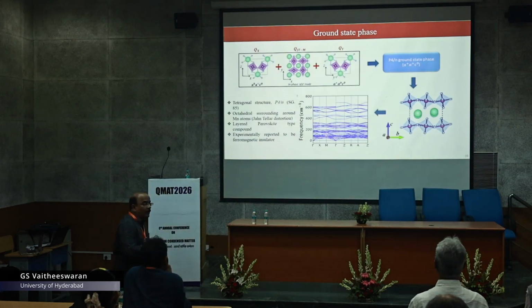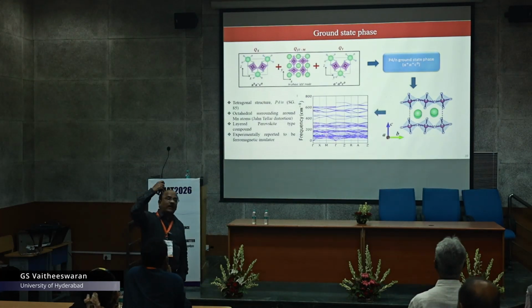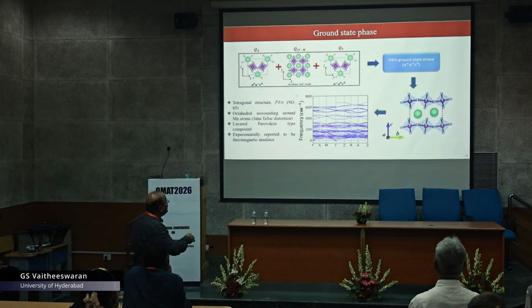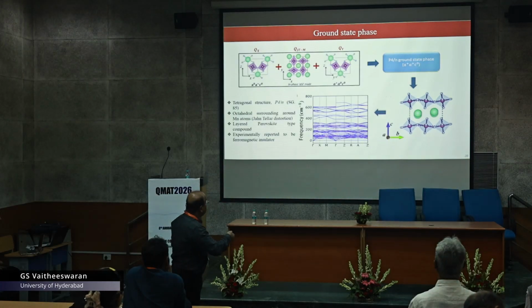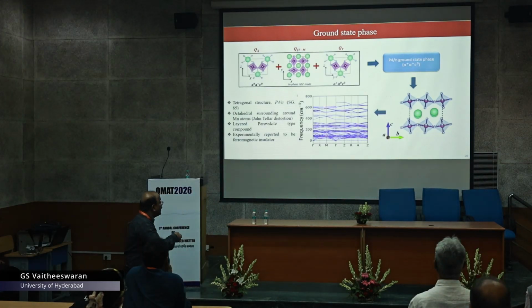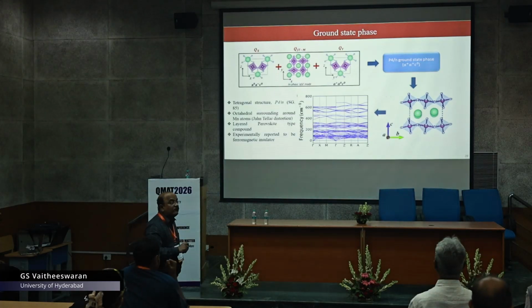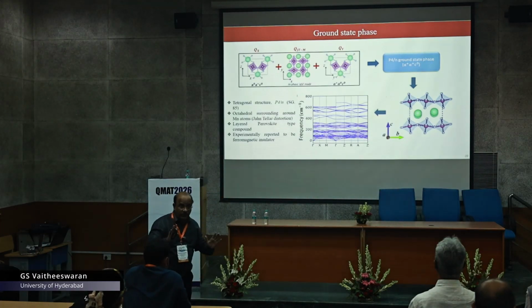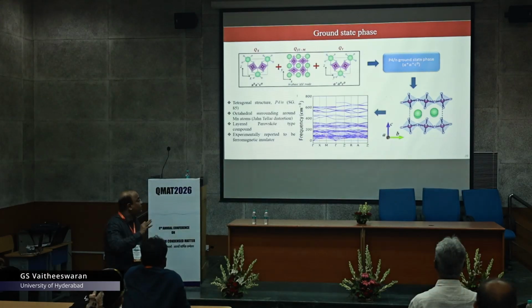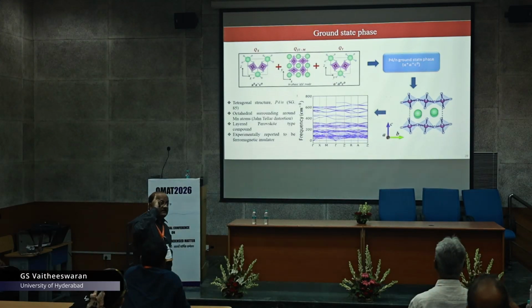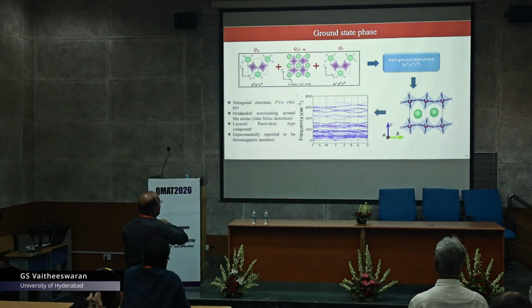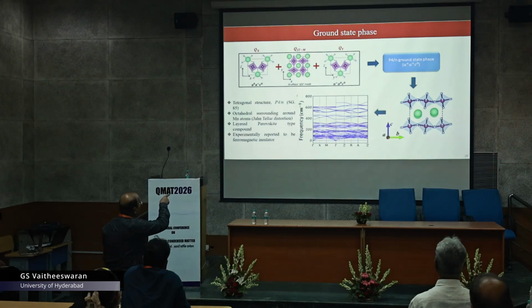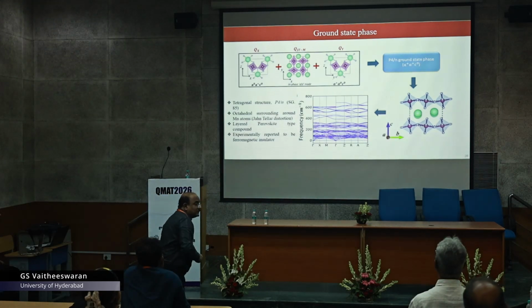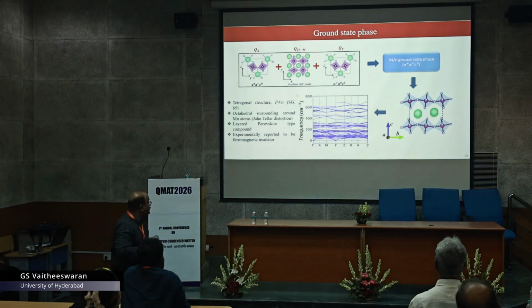Yeah, so then we identified that the P4bar n m m which was proposed by the experiment is not the real ground state. Now when we consider this P4bar n, which is also tetragonal with this kind of Glazer notation, this is a particular ground state where all the phonons are well behaved and we don't have any imaginary phonon modes. This is our conclusion point. As suggested by the experimentalist, Mn3+ is Jahn-Teller active with this particular structure at the M and X points, and this collectively concludes that this particular P4bar n is the ground state.